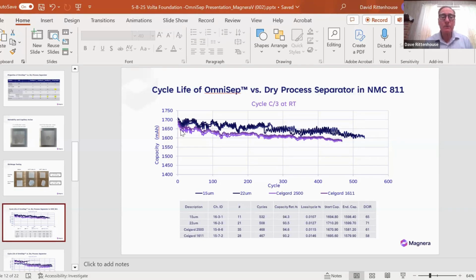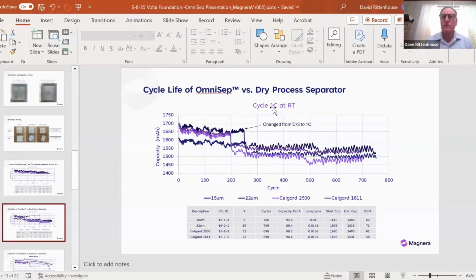For the battery experts on the call, we left the actual data here and only going down to 1400. If it went all the way down to zero, these two lines would almost be on top of each other. But we wanted to give the actual data. So this shows that at C/3 rate, we're at least as good as the best. To get additional data, we changed the cycling rate to 1C to try to tease apart differences. And as you can see, there's the immediate drop in capacity at the 1C charge rate. But again, the OmniSep compared to be at least as good as the best stretched film for that use case.